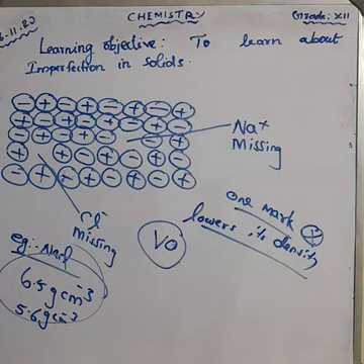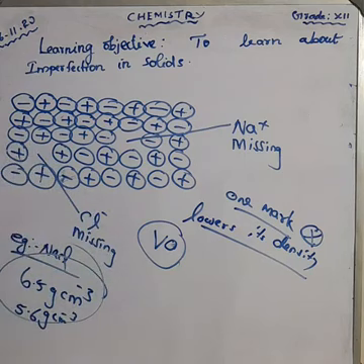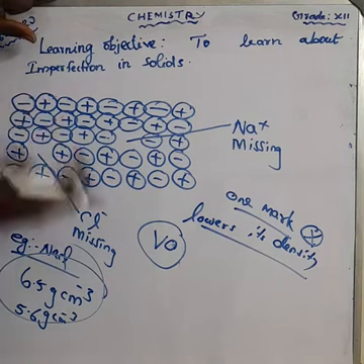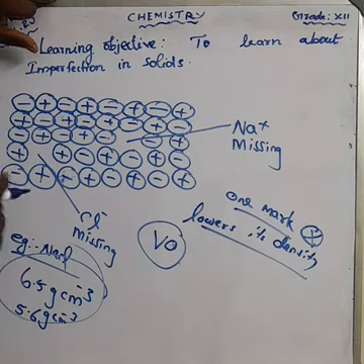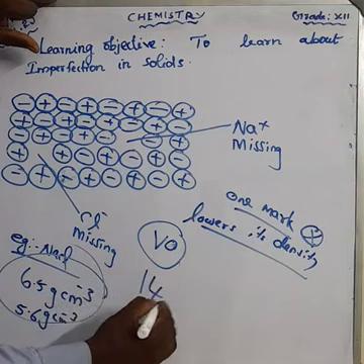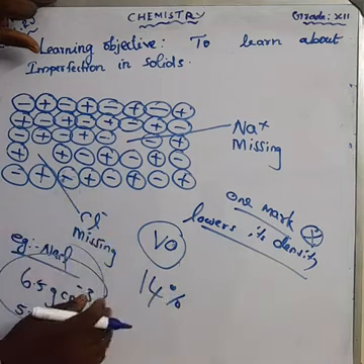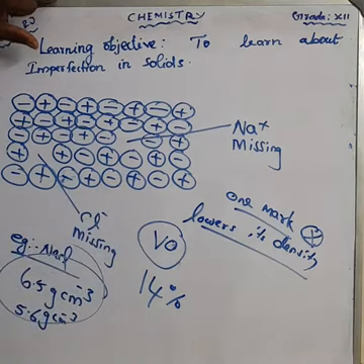The theoretical density of sodium chloride, calculated from the edge length of the unit cell, is 6.5 g cm^-3. But what is the experimental value? 5.6 g cm^-3. It indicates that there is approximately 14% of Schottky defect in the sodium chloride crystal.